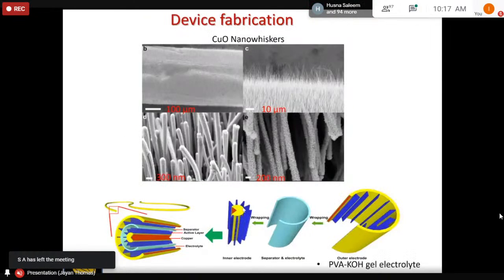Now, with that heating, you can get nanowhiskers with a diameter of about 120 or 140 nanometers, but a length of 20 or 22 microns. So now you can imagine how much aspect ratio you have here. It's a huge aspect ratio, which means that you have a huge surface area, and you got the point, I believe. That means by increasing the surface area, you can store a lot of energy on these fibers. That's how we made these cables.